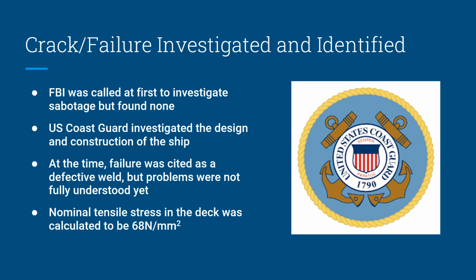So now I'm going to talk about the crack/failure regarding the investigation and how they identified the problem. So at first, the FBI was called because people suspected some sort of sabotage on the ship, but nothing was found. Later, the U.S. Coast Guard investigated the design and construction of the ship. At the time, the failure was cited as a defective weld because problems regarding fatigue analysis were not really well known at the time. And during their investigation, they calculated the nominal tensile stress in the deck to be about 68 newtons per millimeter squared.